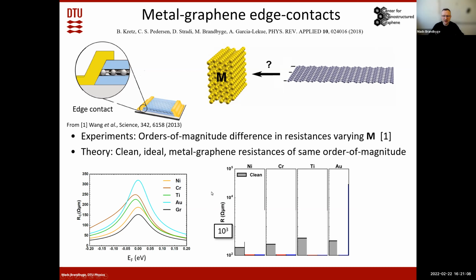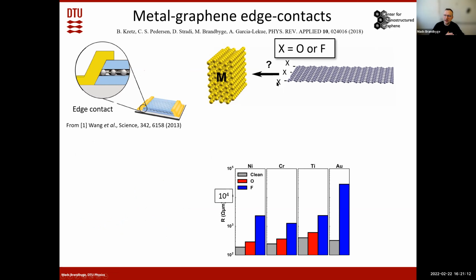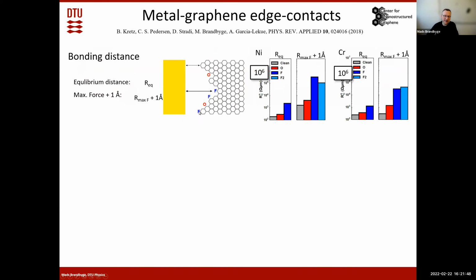So the question is, what happens, for instance, if you have some residues from the etching process, and this will typically be oxygen or fluorine sitting in the contact between the metal and the graphene. If we put that into our calculation, then we see that now the different metals vary by maybe an order of magnitude or two. So this is more in line with the experiments. So we guess that we will not have this perfect contact. We will have oxygen or fluorine sitting there, but we don't have all the variation you see in the experiments. But of course, you can imagine that this is not just a perfect contact, but you will have some roughness. So you will not have ideal distances, but somewhat unideal distances. And then you get a much bigger variation, say 2 or 3 orders of magnitude, which is more like what you have in the experiment.